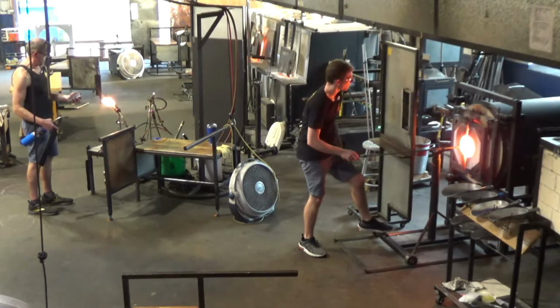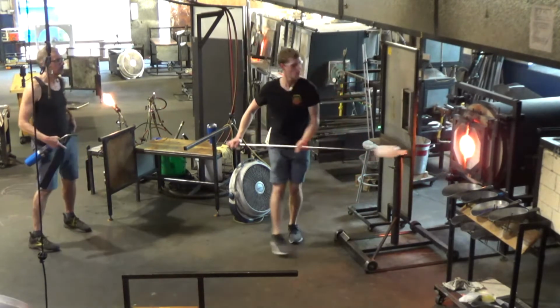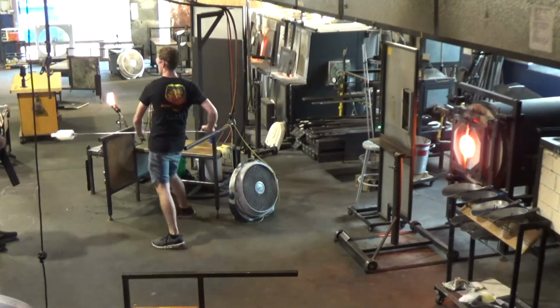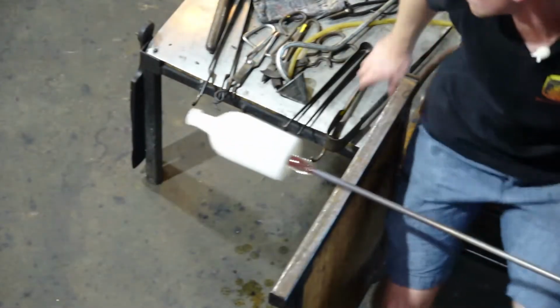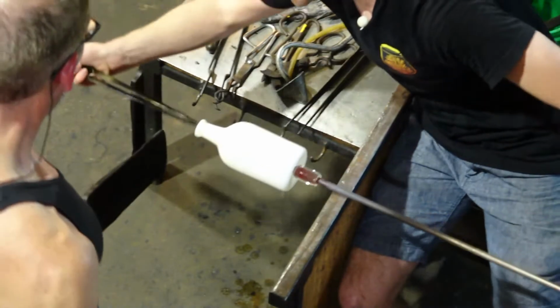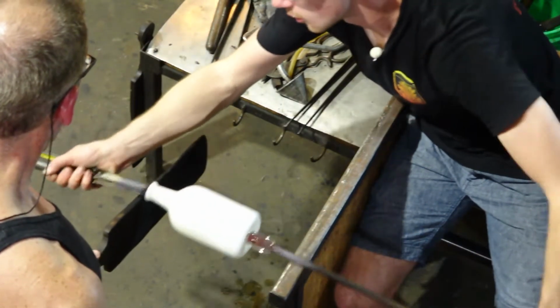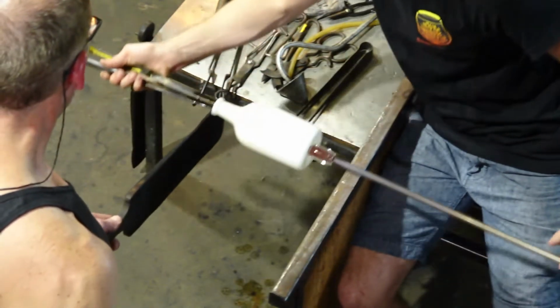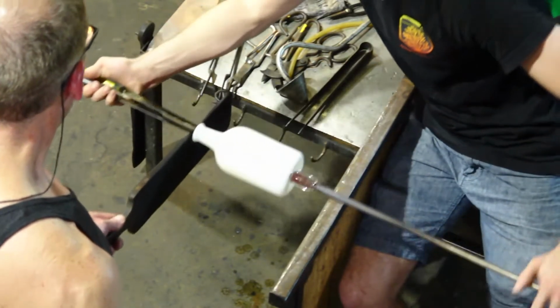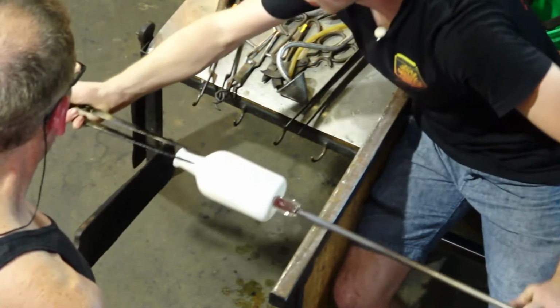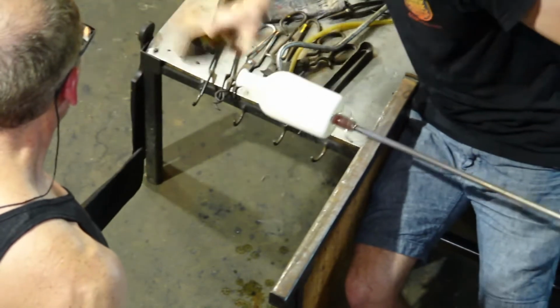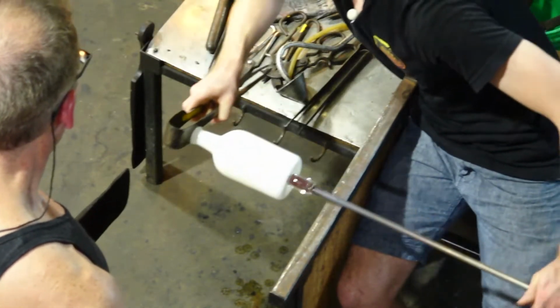You can see these boxes over here. Each of those is computer controlled. It holds the glass at about 950. So we know that it's not so hot that it'll cause it to change shape, but it's not so cold that the surface of the glass will get too cold when we open it and put more pieces in. So once we've filled the annealer up, we tell the computer to send it down, and it brings it down over about 18 to 24 hours.